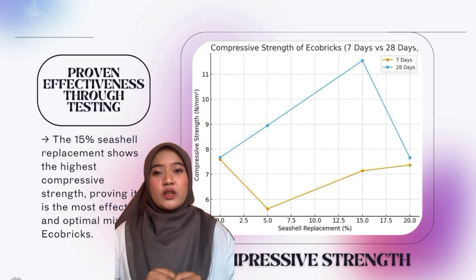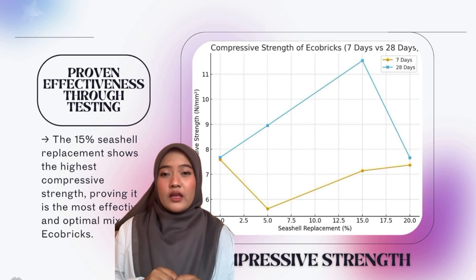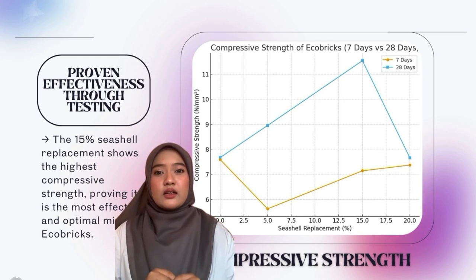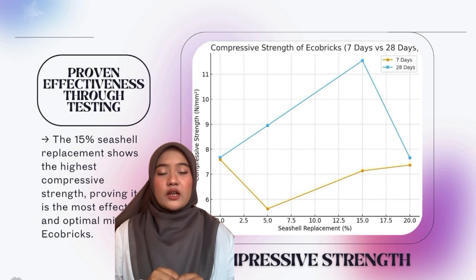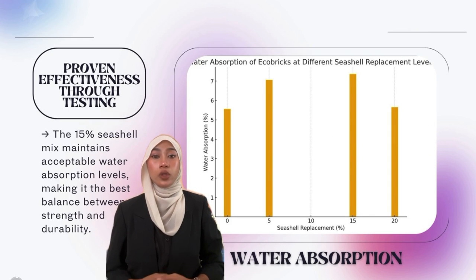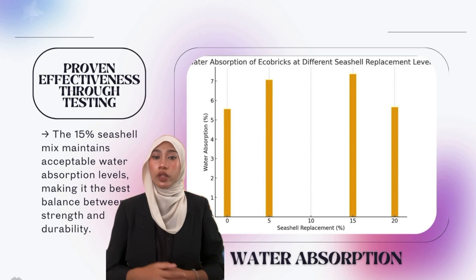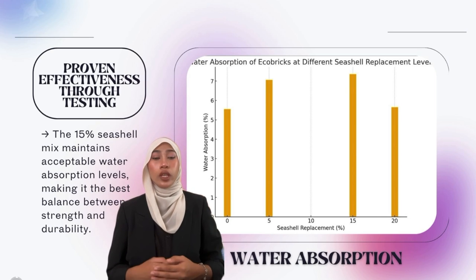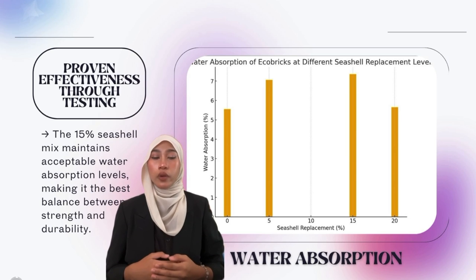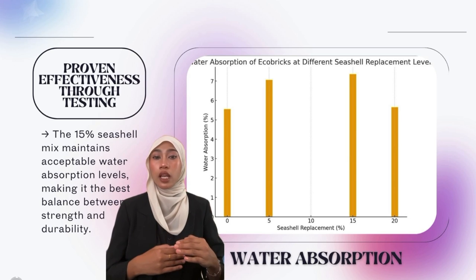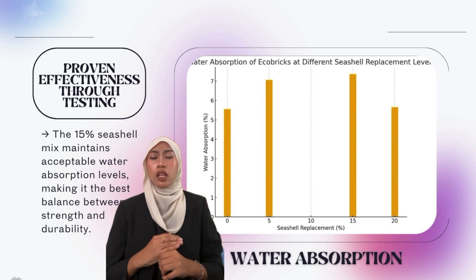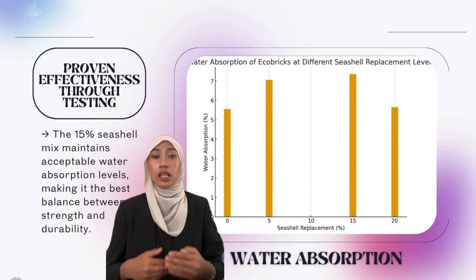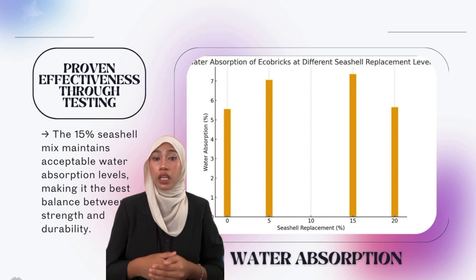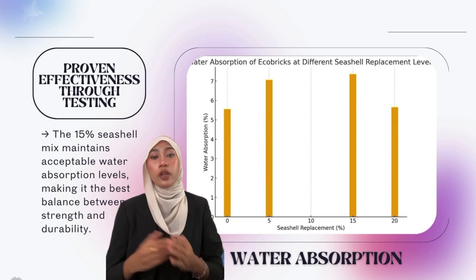For proven effectiveness through testing, look at the graph that shows the 15% seashell replacement has the highest compressive strength, proving it is the most effective and optimal mix for eco-bricks. Next, this graph shows the water absorption results for different seashell replacement levels. We can see that the absorption rate slightly increased from 5% to 15% and then decreased again at 20%. The 15% seashell mix maintains acceptable water absorption levels, making it the best balance between strength and durability.